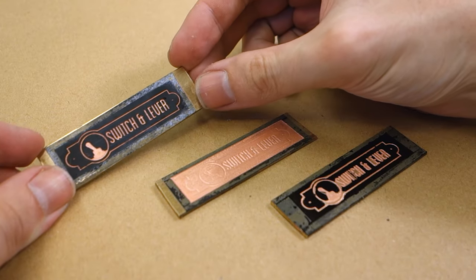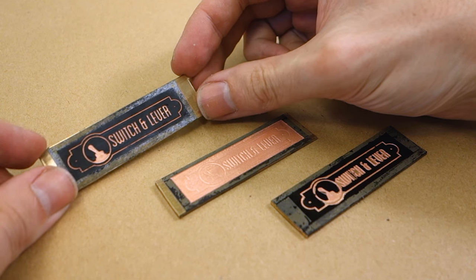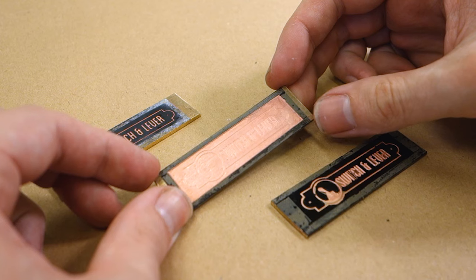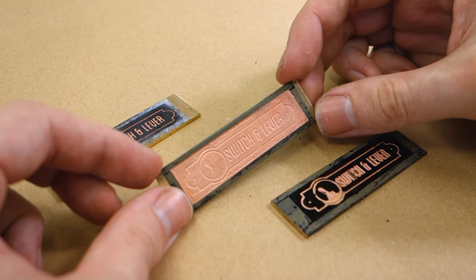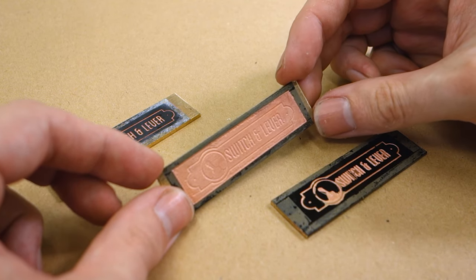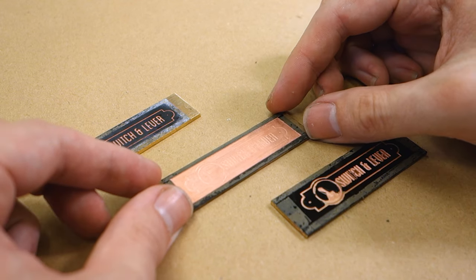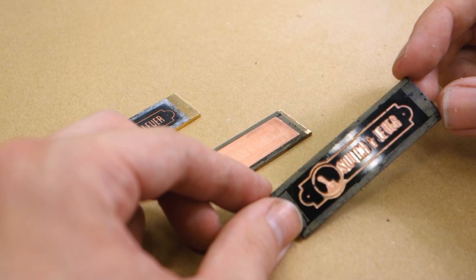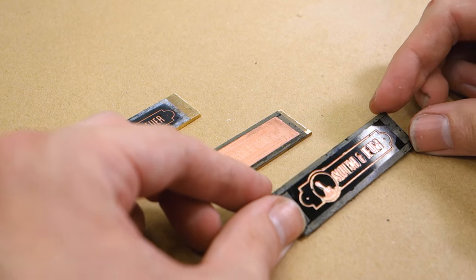As we can see, two of our three plates etched as expected, with the third, our laser marking paint, failing spectacularly. The resist seemed to have worked for a short while until the acid ate it away and started etching the entire surface of the plaque. So at least we can chalk that up as a failure and move on with cleaning the remaining two plaques.